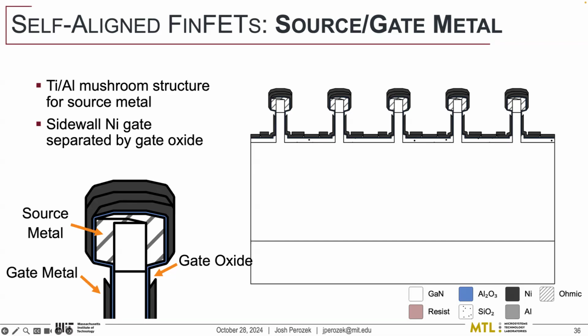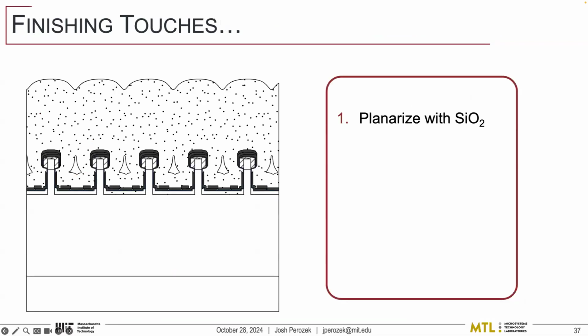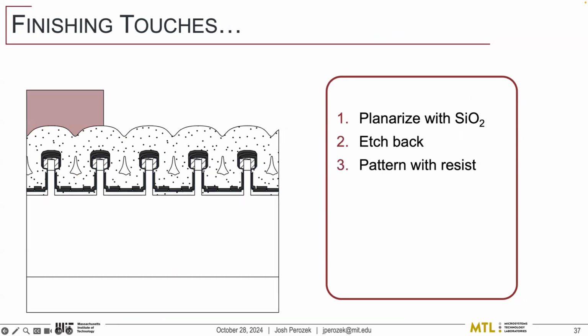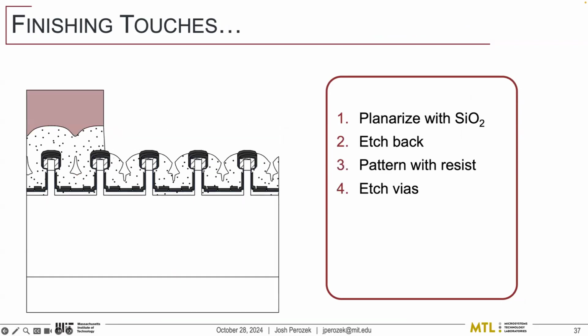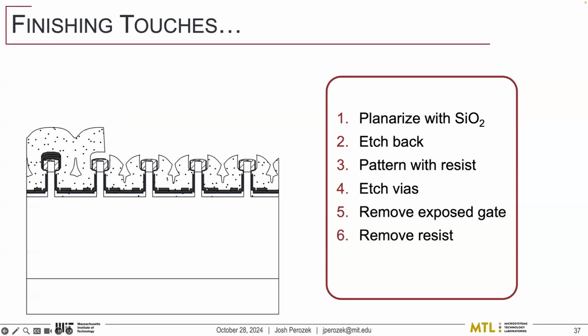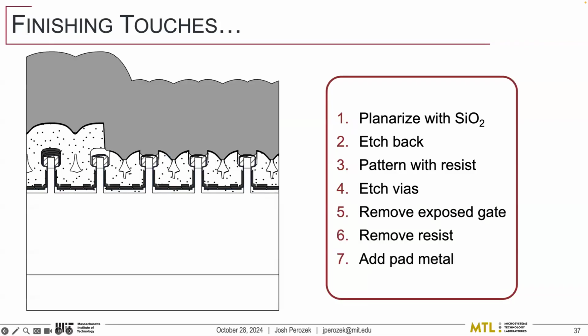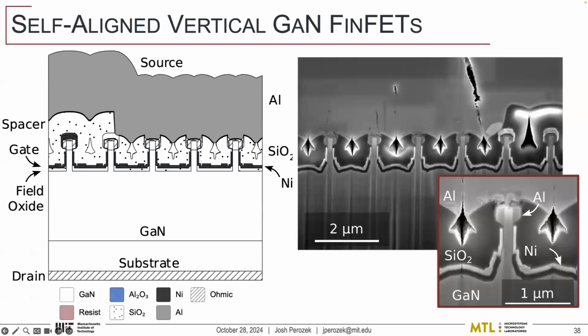It's a standard recipe. To finish it off, it's kind of the same stuff that we've always done. You planarize it with more oxide, you etch it back, open a via, but now the gallium nitride's all protected, so that's totally fine, and nickel's actually super robust, and we remove it anyways in the next step. Put our contacts in, remove the resist, put our pad metals on, and we make these devices.